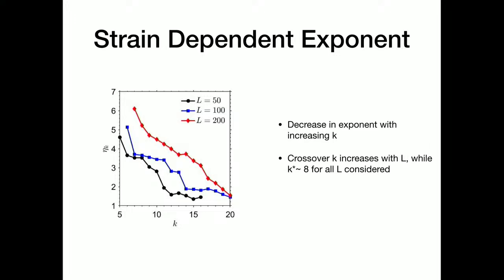Things to note here is that the crossover K that we saw earlier was increasing with L. While K star, so this is the crossover, it's not very well defined as you increase the system size, but the crossover from a high exponent to low exponent happens somewhere, and you can see that that transition is later and later as the system size is increased, which makes it not a very good way of looking at it, because you are coming closer to final failure as you are moving.